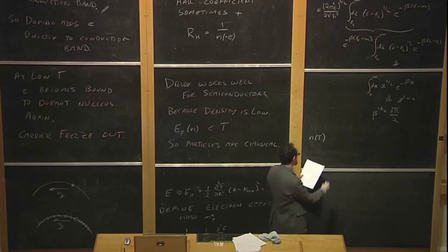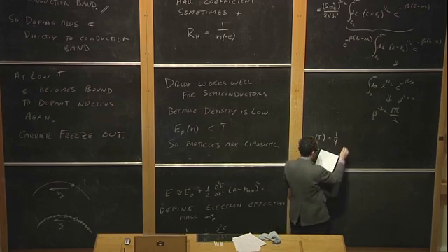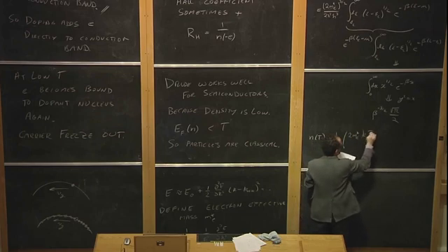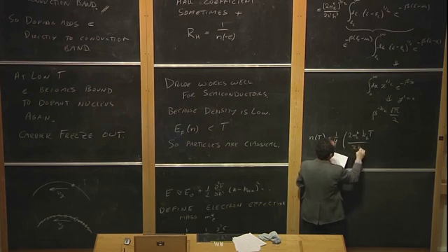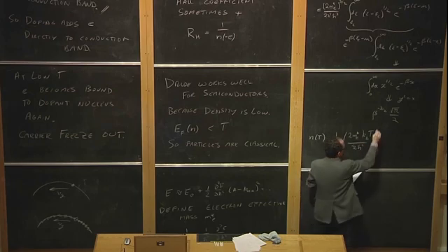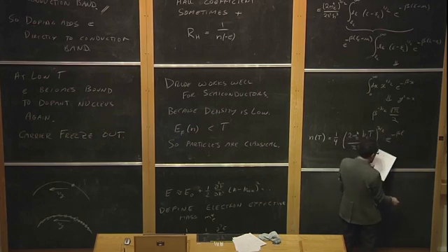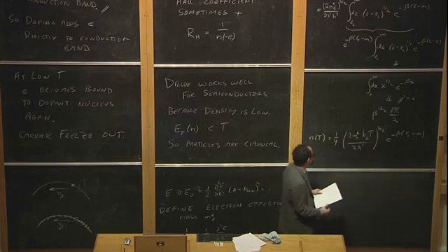Okay? So we put that all together, and we end up getting the density of electrons in the conduction band as a function of T, putting together all those factors, 1/4 times (2 m star k_B T over pi h bar squared) to the 3/2 times e to the minus beta (E_C minus mu). So this is our expression.